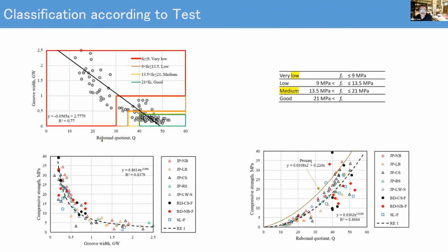If we look at the evidence, we can see there is a direct correlation between the rebound coefficient and the groove width. If the rebound coefficient increases, the groove width decreases because it is a stronger concrete. But if the rebound coefficient decreases, the groove width has to increase for the low strength concrete, and this part is basically a very low grade concrete. But the part we want is 21 MPa or more strength. This is our minimum expectation, that our buildings are above 21 MPa. That is the major part. Then we will have something here, or something here, or unfortunately if we have something less than 9 MPa, then we cannot move forward.